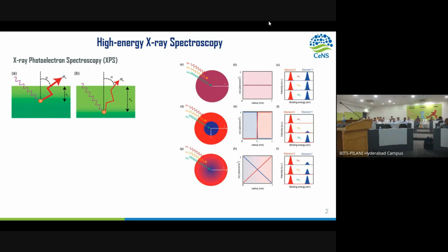Using this technique, you can determine different heterostructures inside a heterostructured nanoparticle. This is possible because the mean free path of the photoelectron, which we can tune when using photon energy up to 6000 eV or 8000 eV, is in the dimension of the size of the particle.